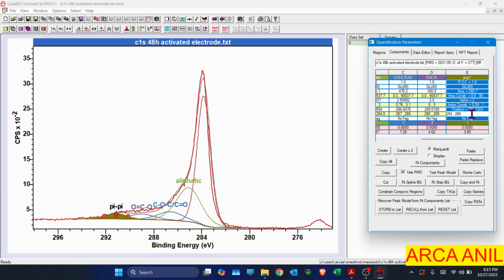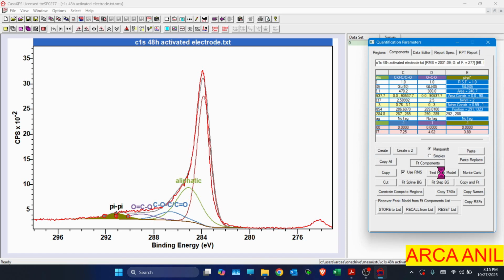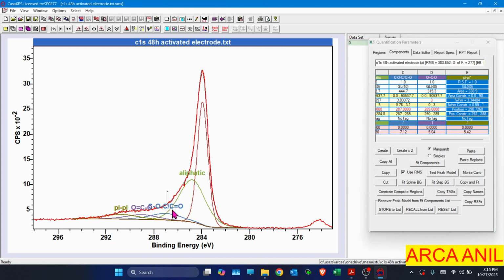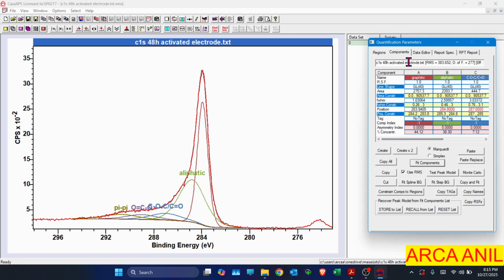Okay, and I think we can fit the components. I will constrain the region, okay, and I will hit fit. So I think it is a pretty good fit. So we have a pi to pi transition here, ester group here, carbon oxygen carbon or ketone group, and aldehyde groups are here. So we have an aliphatic peak here, and we have a graphitic peak here.